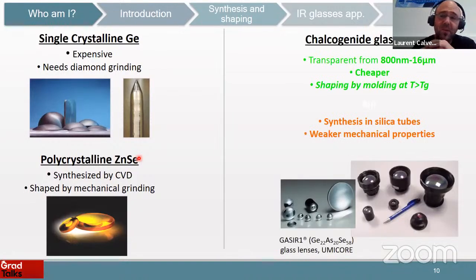So there is an alternative here, which is the chalcogenide glasses. This is what we are working on in the lab in Rennes. Why do we want to use these chalcogenide glasses? Because these materials, even if they are not transparent in the visible, are transparent in the infrared, very close to the visible, 800 nanometers, up to 16 micron, and even more.